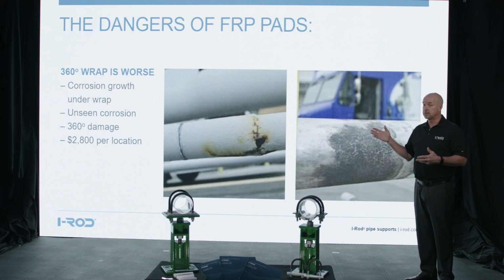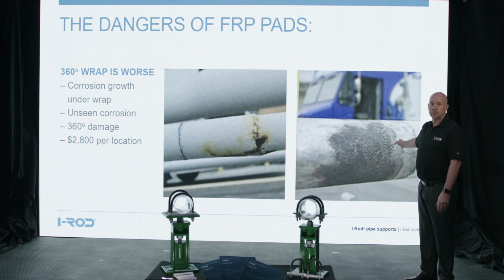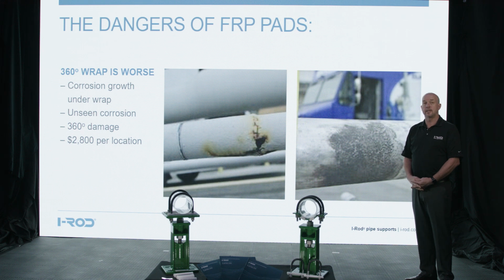This is an unseen corrosion. You can't see it because it's all covered up. And the worst thing is this can be a 360-degree damaged area. You'll notice here on the right there's corrosion pitting and metal wall loss happening almost all the way to the top of the pipe because the fiberglass wear pad has allowed moisture to get in and trap it against the steel pipe. This is the worst case of all of them.